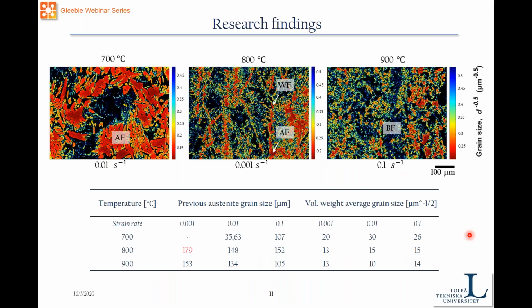Further analysis was done using an open source script in MATLAB that is based on the Hall-Petch number, and this could give us an approximation of the austenite grain size in non-homogeneous structures. So we measured the previous austenite grain size in the material and the volume weighted average grain size. I'm not going through in detail how I calculated it, but I will give you the link later on in case you are interested in the methodology and the numerical approach in this research.